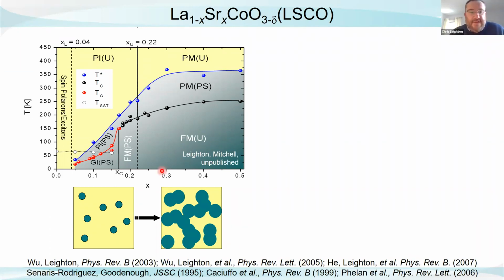The other is the magnetic phase diagram shown here, and I won't go through the magnetic phase diagram in a lot of detail. I don't think I need to, but what I will point out is this is a classic example at low doping of a magnetically phase separated system. So when this system is lightly doped, it forms these ferromagnetic hole-rich clusters that live in a non-ferromagnetic insulating matrix. And then there's a percolation threshold at about 18% doping, x is 0.18, where those clusters connect into a long-range ordered ferromagnet. So we get a transition from a glassy insulator to a ferromagnetic metal.